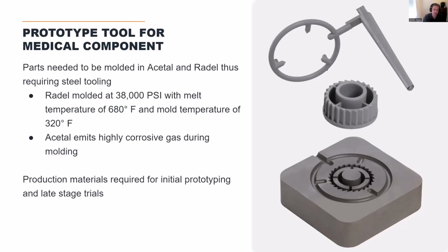They were told the Radel was molding at 38,000 psi with high melt temperatures and mold temperatures, and then the acetal was emitting some corrosion gas, which made aluminum tooling not an option here for this prototyping stage. They also wanted to use production materials for their tooling because this was going to allow them to get through both initial prototyping and some of the late stage trials that were going to need to happen, because they were using a production representative or production equivalent tool early in the prototyping stage. They're able to use those same parts, which they wouldn't have been able to do if they had machined those parts or if they had used an aluminum prototype.